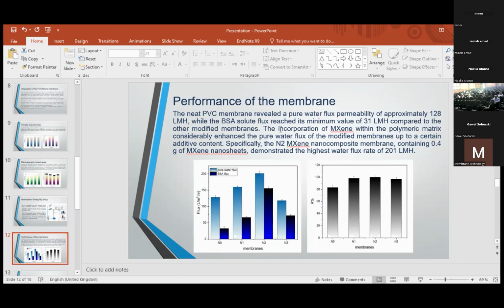Compared to the other modified membranes, the incorporation of MXene within the polymeric matrix considerably enhanced the pure water flux of the modified membrane up to a certain additive content, especially the N2 MXene nanocomposite membrane, which contains 0.4 gram of MXene nanosheets, demonstrating the highest water flux rate of 201 LMH.